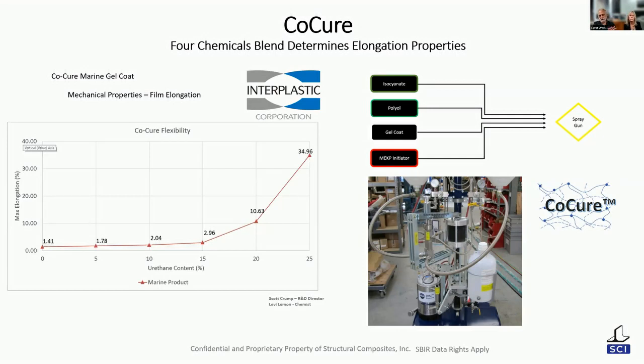And you can see nothing much happens till about 10%. Then we start to shift. 15% is an economic sweet spot. That elongation matches our inexpensive resins on our boats. It gives us about double the impact resistance, double the color change resistance, double the weathering resistance, double the abrasion resistance. And that's a nice spot to be at, 15% urethane.